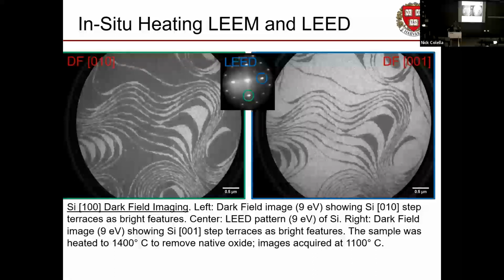So, heating and cooling. This is an example of what happens when you get something really hot and you look at its surface. These are 2 different sets of atomic planes. Sets of atomic planes, meaning different orientations of the crystal. And this piece of silicon happens to have a crystal structure such that if you have a rough surface, you get alternating 90-degree turns in the crystal with each atomic set the surface has. And so we use a dark field mask, and we take that spot and put it over here, that spot over there, and we get these 2 images of the different planes. And that's all very nice.